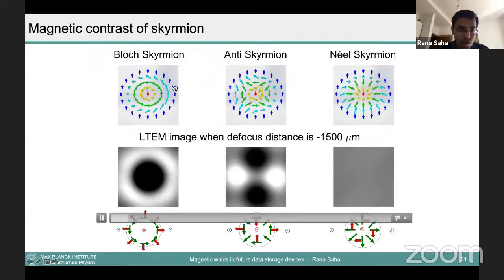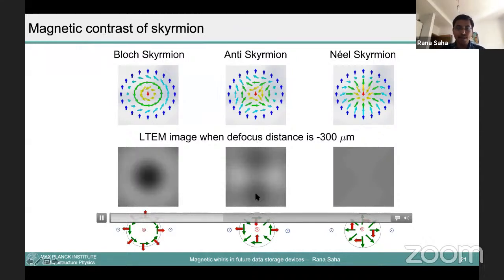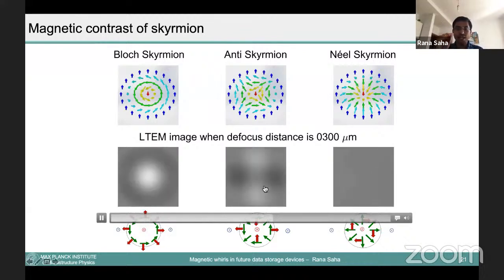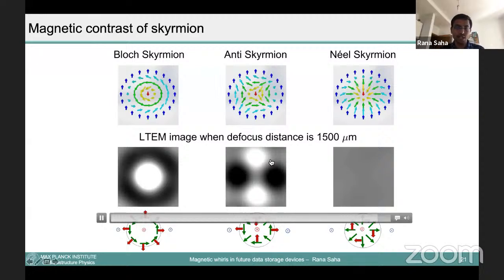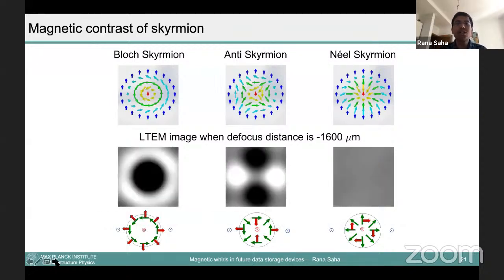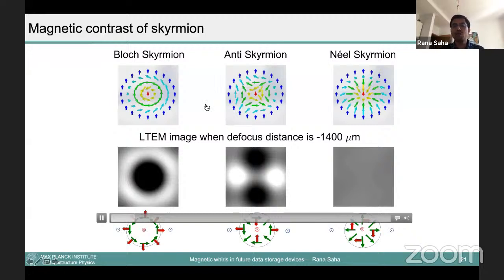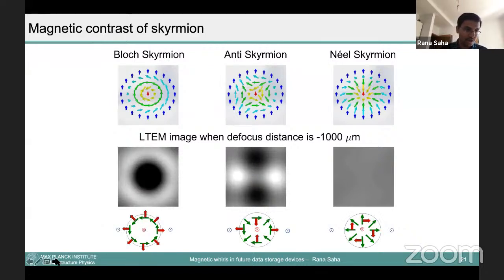And because of this magnetic contrast, they will look like that. So you have a Bloch skyrmion, which has this kind of contrast. If you have a Néel skyrmion, you will have no contrast. But when you have an anti-skyrmion, which I'm interested in, you can see here, there is no contrast, and when this defocus happens, the contrast is generated something like that. So you have some kind of clover-leaf structure where there are two bright and two dark spots. If you have this kind of contrast, this way we can actually detect this spin structure. So this is really interesting.